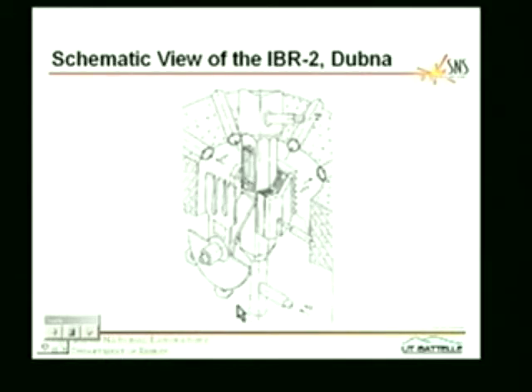This shows you the design. It's got plutonium oxide fuel in the fuel here. There's a reflector surrounding it. And then this is a reflector. These things that look like scissors are counter-rotating reflectors. And what happens is they spin around, and when they line up, then the reactor is critical. So that's the on position. And then when the reflectors rotate out, that's the off position. It's no longer critical. So the power cycles as these things spin around.